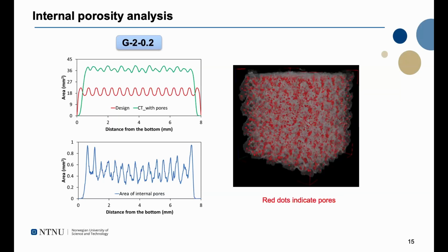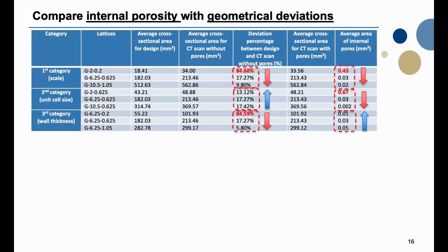And internal porosity analysis was also determined in this case. Here we use the CT scan to determine all the layers of the lattice structures, and this area represents the cross-sectional area. As we can see, there is a huge deviation between the scan and the CT files of the areas, and this is the lattice with the smallest dimensions. And there are internal pores here. The reason this has fluctuating trends is because of the boundary effects of each layer. And from the file, we can see that the red dots indicate the pores, and this is for the specimen with the smallest geometry.